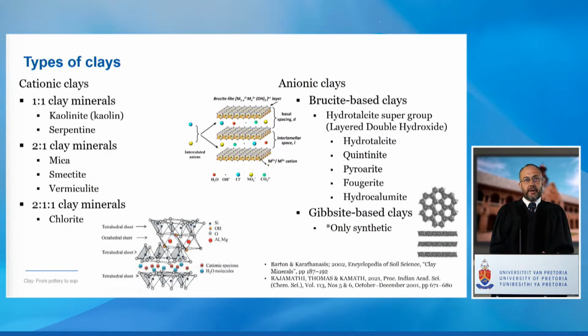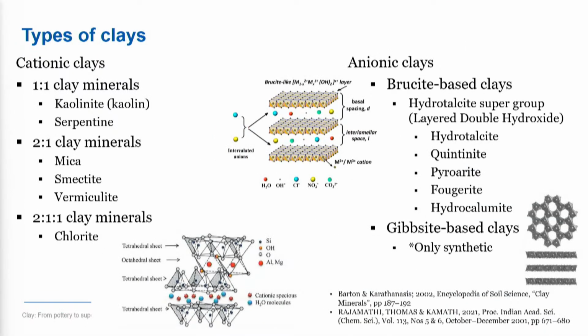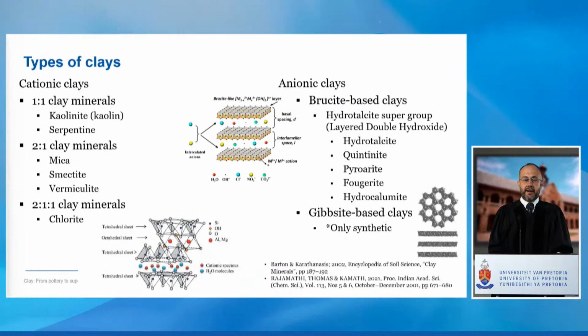Clays are typically broken up into 2 distinct groups. We can have the cationic clays and the anionic clays. Cationic clays, as the name suggests, have cations as an interlayer to balance the structure. So clays are made up of platelets with their own charge. If the ion in the interlayer is positively charged, we refer to it as a cationic clay, and if it's negatively charged, we refer to it as an anionic clay.